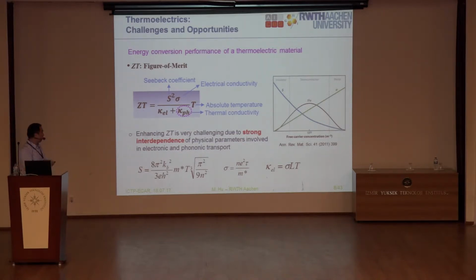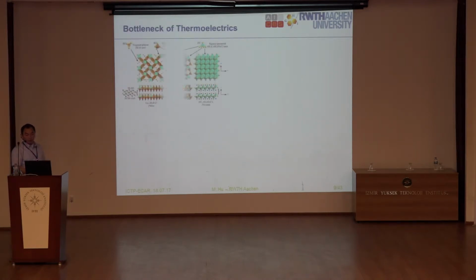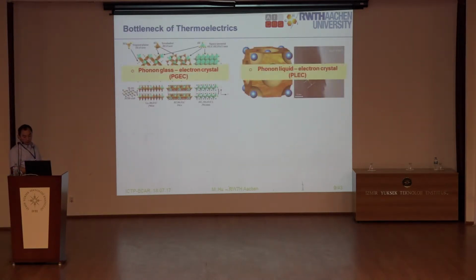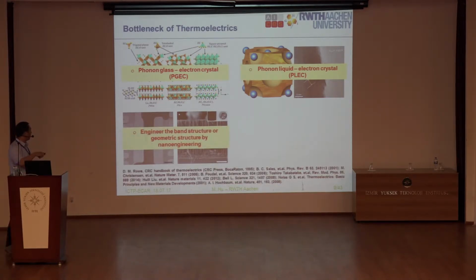So far, most research, of course, is focused on how to reduce the thermal conductivity of the lattice part. This is because this is the only part that does not have a strong dependence on the electronic structure. So there are some studies focused on different concepts. For example, the major concept is the phonon glass electron crystal. You can make the crystal structure very complex so that the phonon scattering is very, very strong, and then you can minimize the phonon transport while in the meantime the electronic transport can remain large.